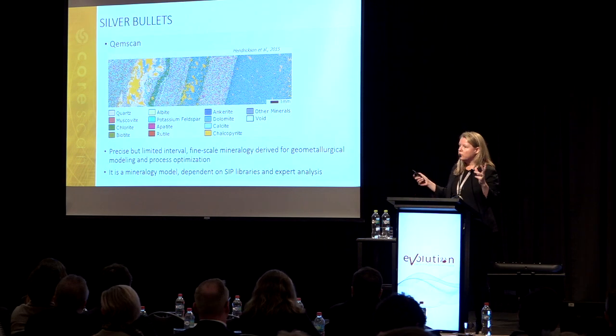But this isn't a silver bullet. It isn't this one thing you can do, and I don't need to do anything else. I'm just going to do QEMSCAN, and I don't need to do anything else for my MET testing. Any of the providers of QEMSCAN here would tell you it actually can be difficult to do clays, for instance. Well, there's another technique that can do clays really well, and that's infrared. So you can use them together.